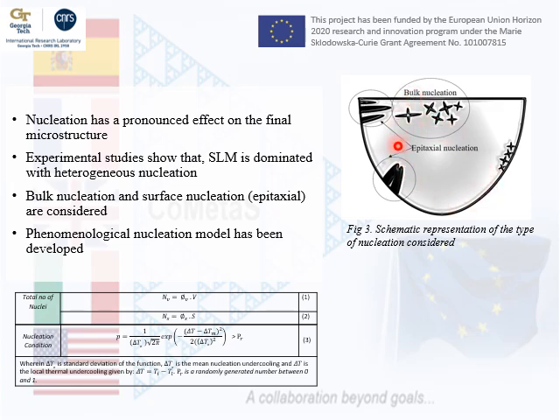So we consider epitaxial nucleation. Epitaxial nucleation occurs along the solidification line, and this normally corresponds to the grains that form at the border of the melt pool, and they grow in a directional way. In addition to that, we can also consider bulk nucleation. This happens in the melt, and normally they have random orientations. In the case of epitaxial nucleation, the orientations of the grains are very directional.